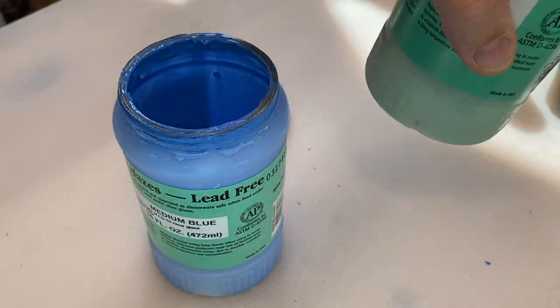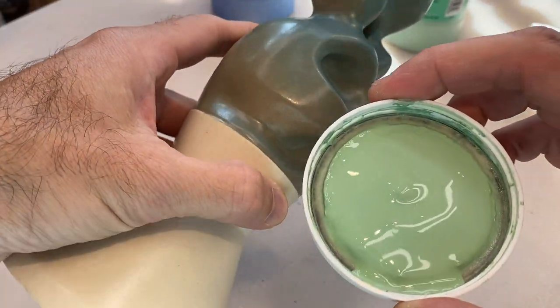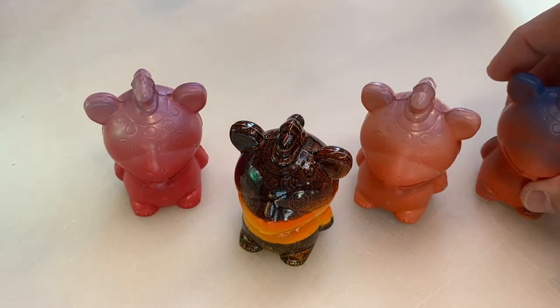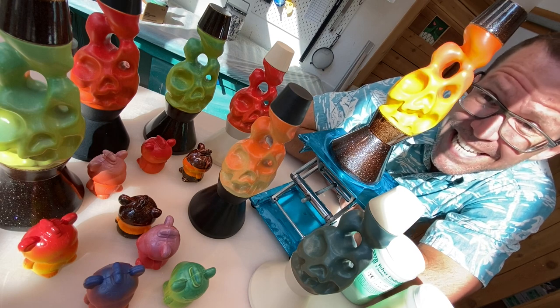That being said, there are tricks with it. Sometimes when you fire it, it will look great at a low fire temperature, but not at high fire — and I fire things very hot. I sprayed these onto a test piece and fired it to cone six, and look what happened: the green turned to like an icky dirt color and the blue really darkened. So with this color shifting in mind, we've been doing test after test after test. It has been glaze testing mania.